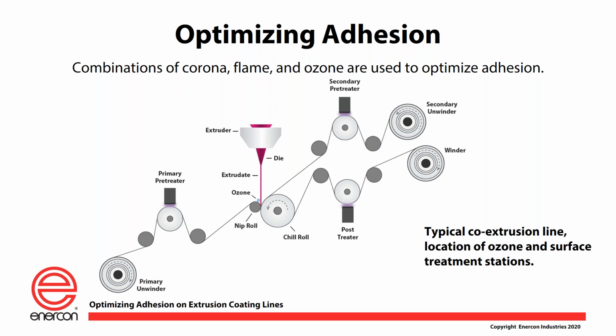Now I'm going to focus a little bit on one other area here that's important, because we're going to touch on this as we go through the presentation. If you look carefully into that nip area, you're going to see a terminology in there called ozone. Ozone treatment is a very interesting technology. It really is what it sounds like. We generate ozone gas, and we apply it right at the nip point of the extrusion process. So the extruder is dropping the extrudate down into that nip area, and at that same juncture, we gently apply ozone to that extrudate.